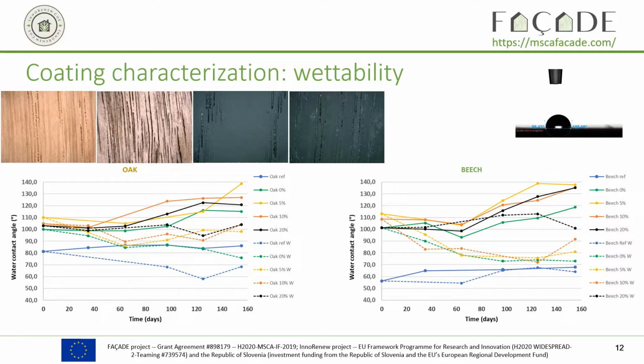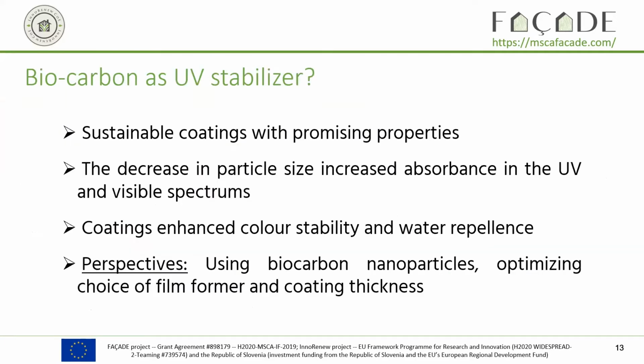And the next picture is for 20% carbon in the coating. So we can see that with 20% carbon, there are still some porosities at the surface. We did not manage to cover all the porosities of the surface. And after 5 months, this porosity is increased, even though we are using the coating.